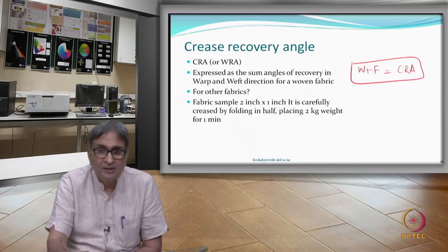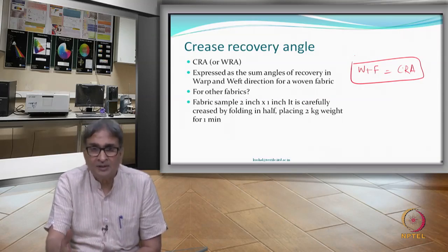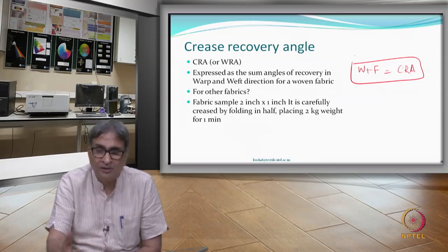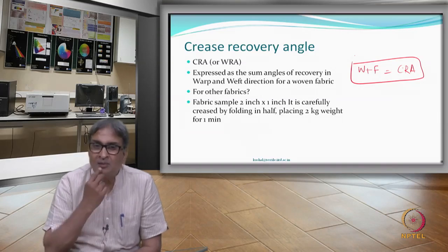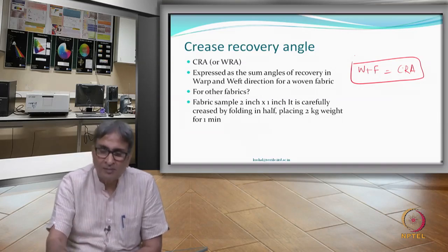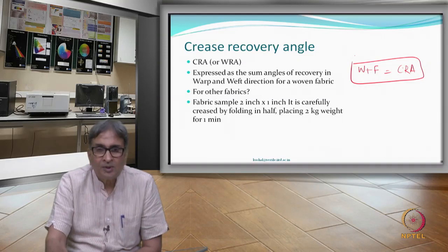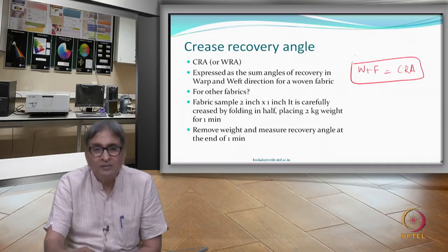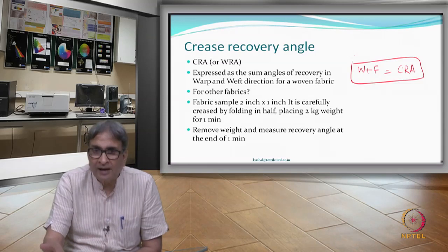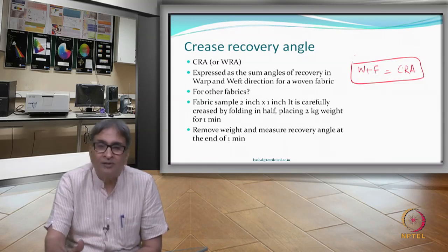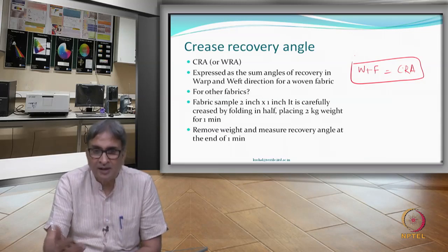The test involves cutting samples to certain dimensions — for example, 2 inch by 1 inch. Then bend them, fold them, and put a certain amount of weight for a certain time — for example, 2 kilograms for one minute. Then remove the weight and measure the angle which has been recovered after removal of the weight, after a set period such as 1 minute.